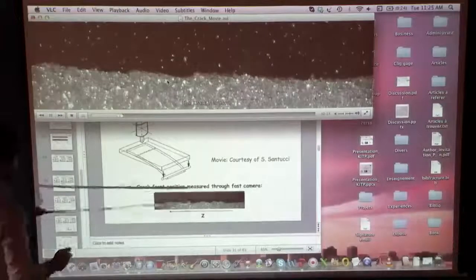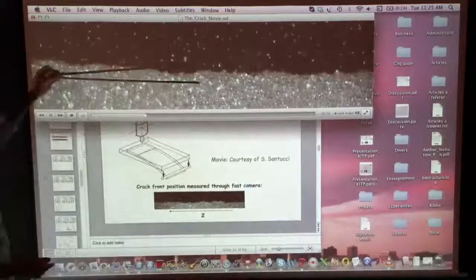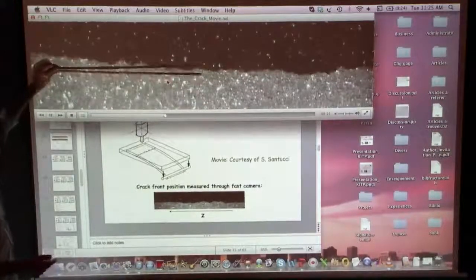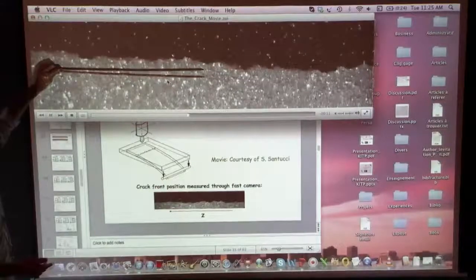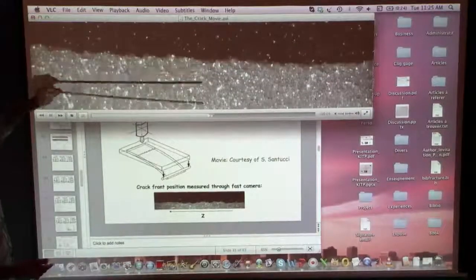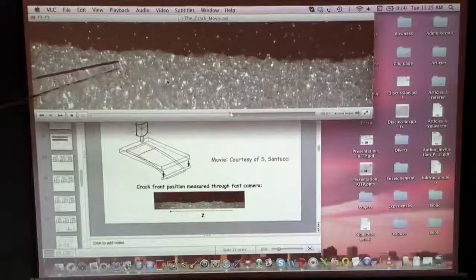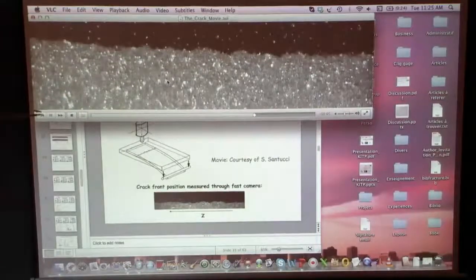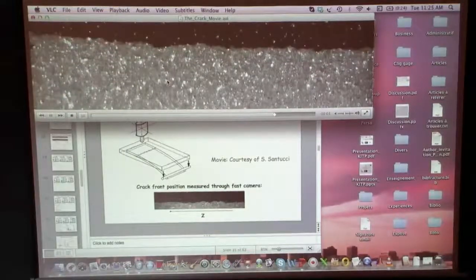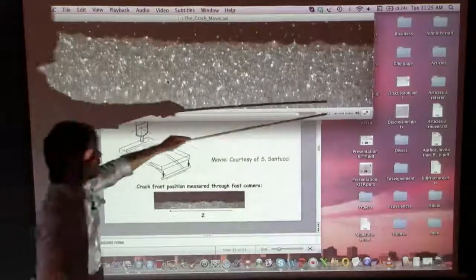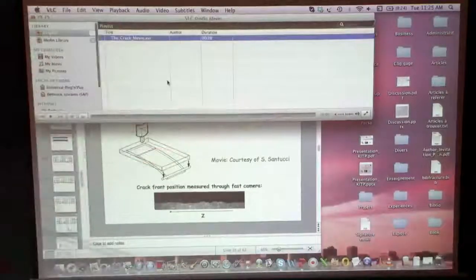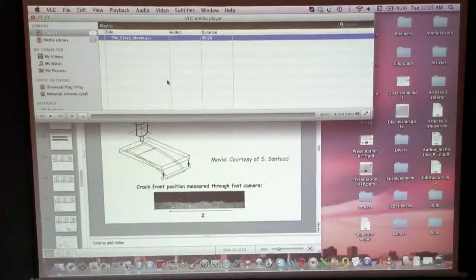At the interface, they measure the crack front position using a fast camera. They record it at some high frequency, and you see avalanche-like dynamics. The typical size is a few centimeters, and the movie is accelerating. I think it's 1 minute.